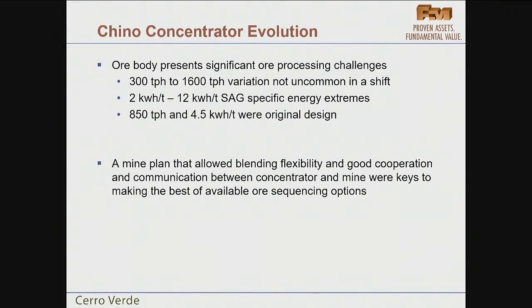One of my first experiences at Chino was as a control room operator, and these are some of the variations you could see on a 12-hour shift basis, 300 to 1,600 tons an hour. I remember some nights having to stand by the feeders, the button on the feeder, turning them on and off, and run the SAG mill batch because the ore was so hard. Very extreme specific energy conditions, and then the average is about 4.5 kilowatt hours a ton.